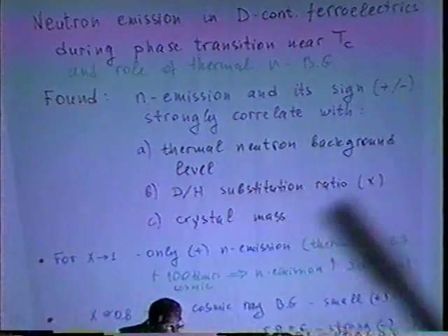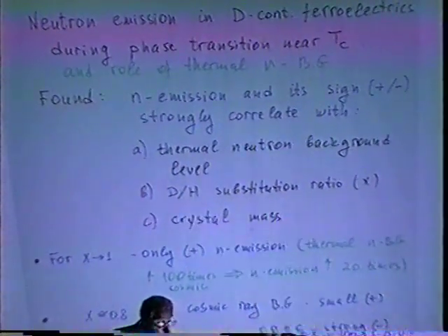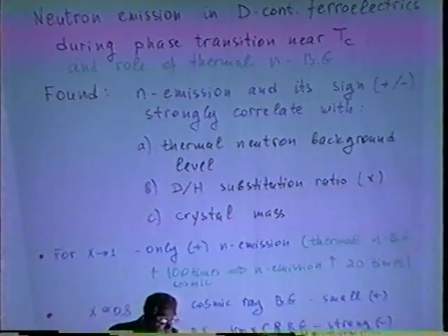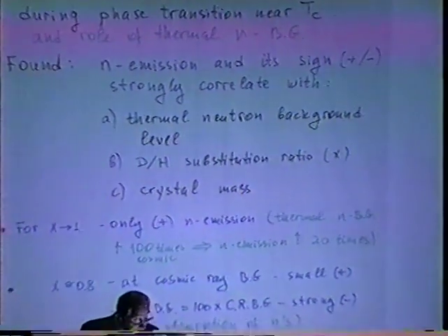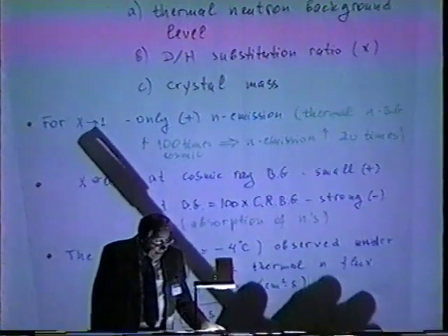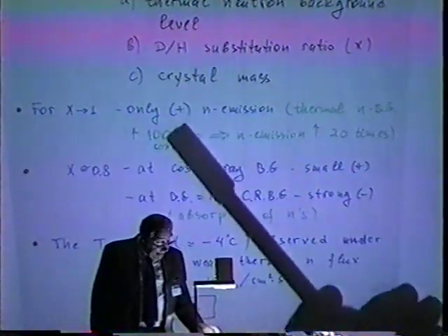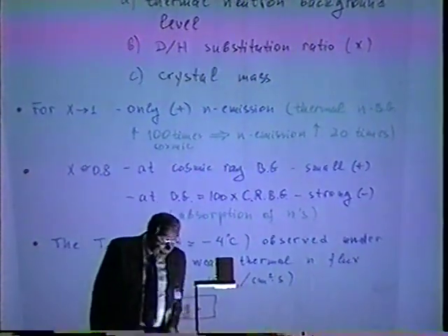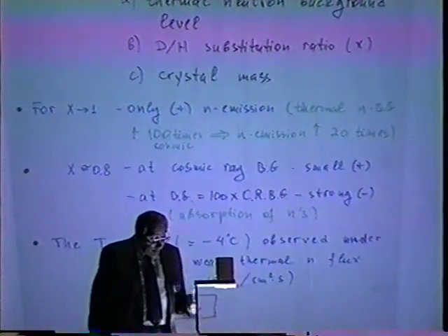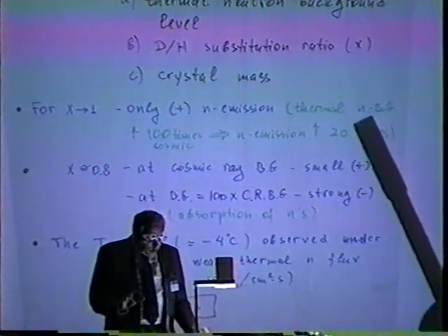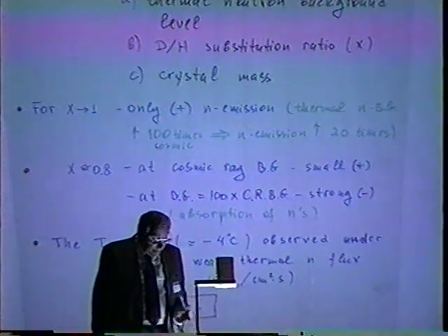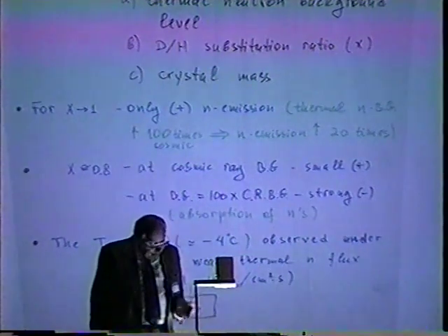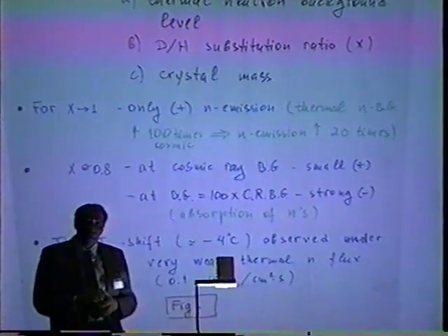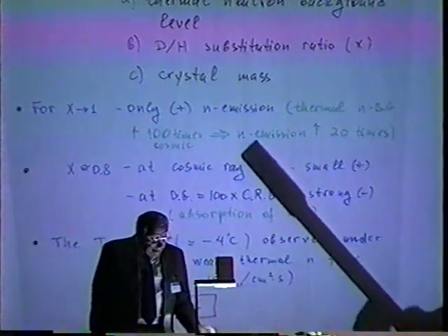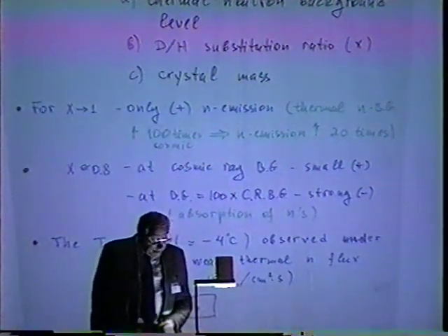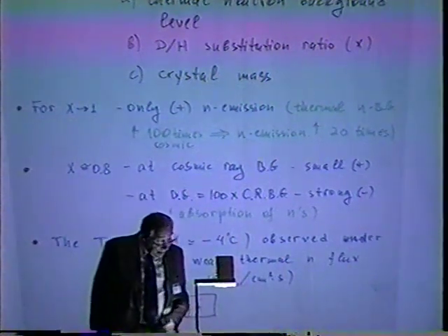three points. First, with the thermal neutron background level, with the deuterium to hydrogen substitution ratio or saturation ratio, and with the mass of the crystal. They observed, for example, that when X is close to 1, then there is positive neutron emission. What does it mean? It means that if they irradiate their sample during phase transition with very low intensity thermal neutron background, which maybe is not too low, but is about 100 times larger than the natural cosmic ray background, they observed that in this case the emission of fast neutrons also increased about 20 times.